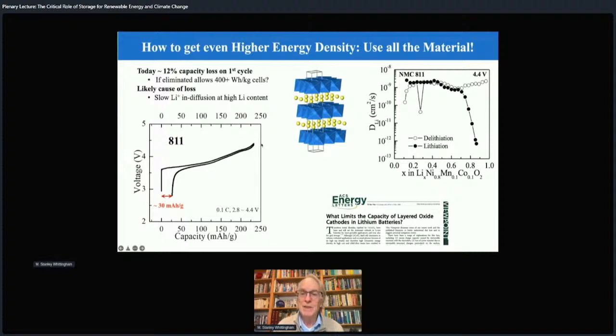And in fact, we measured this. And here's the lithium diffusion coefficient here. It's about 10 to the minus 9 centimeters squared per second until we've got about 75, 80% of the lithium in. Then it falls off the cliff, dropping by over three orders of magnitude. We now know that this is due to what's known as a divacancy mechanism. So for a lithium ion to jump in this lattice from this point to this point, it needs two vacancies. There are fewer and fewer of these divacancies as you fill the lattice up.